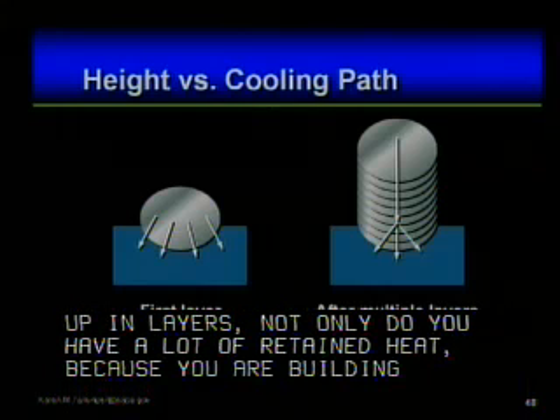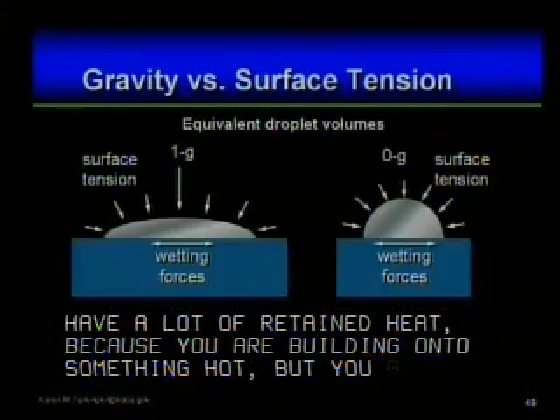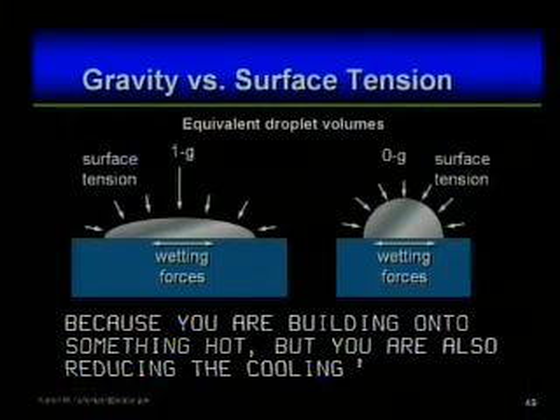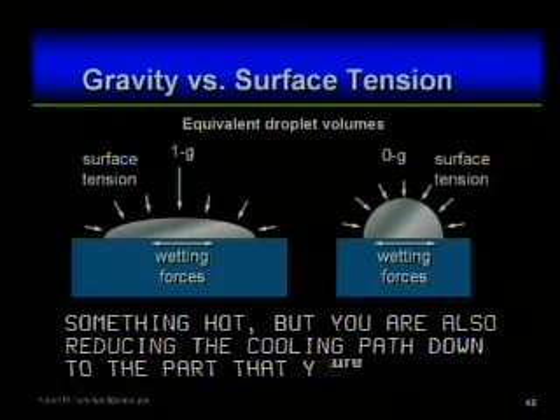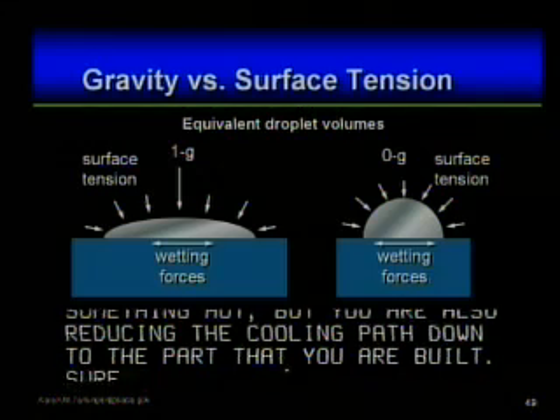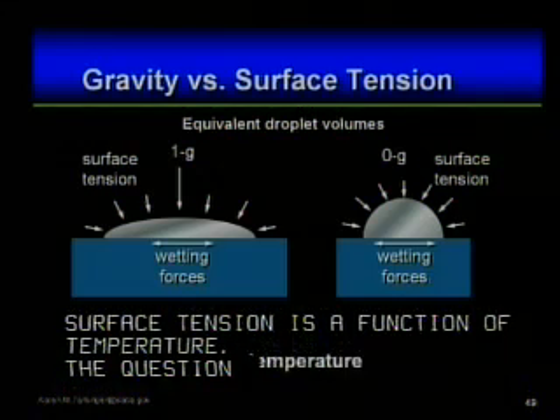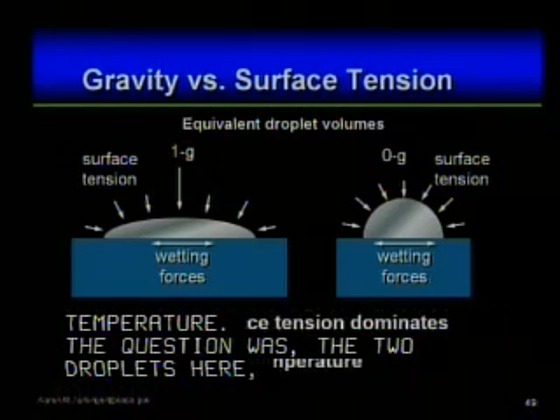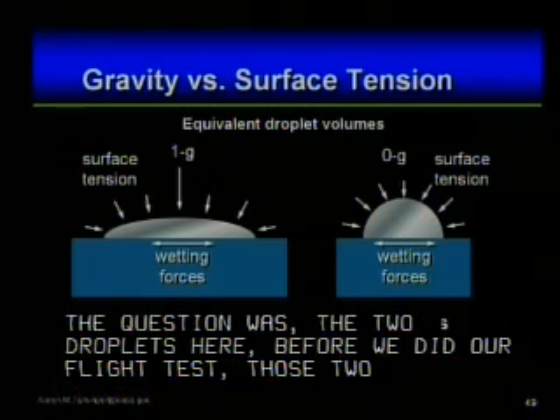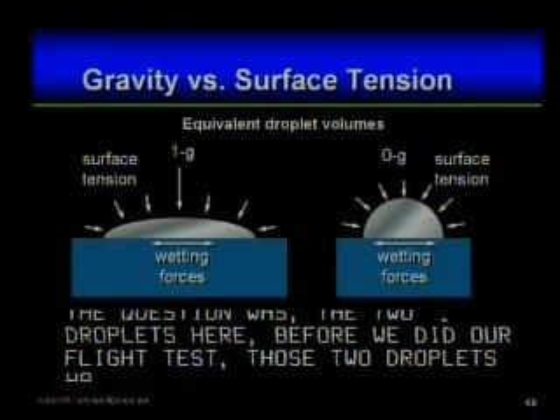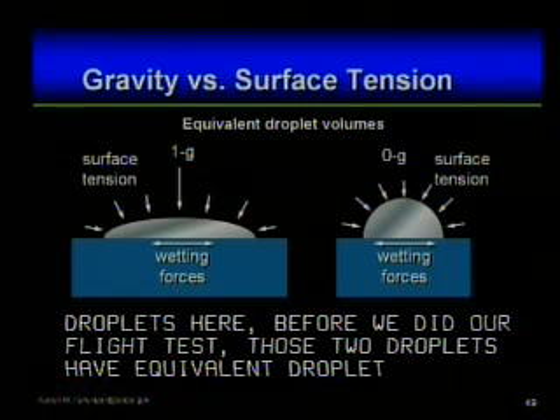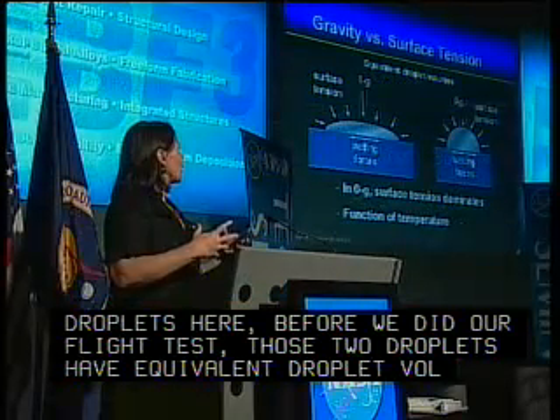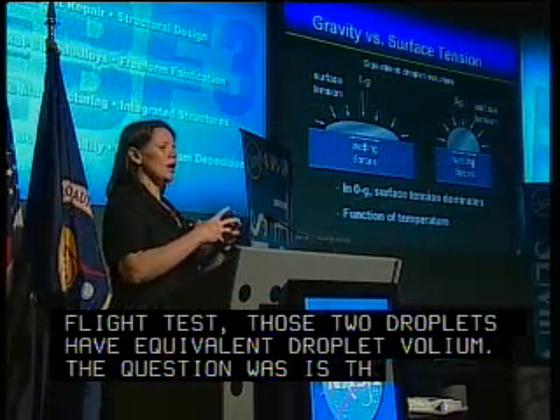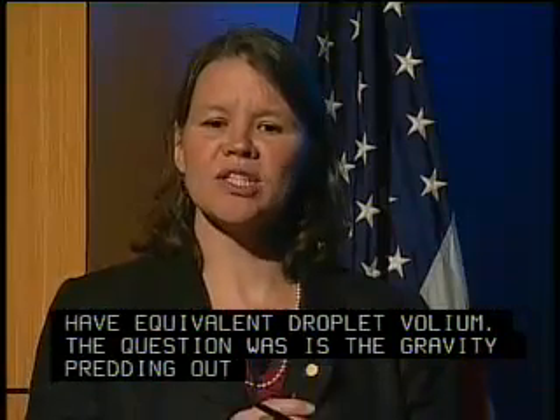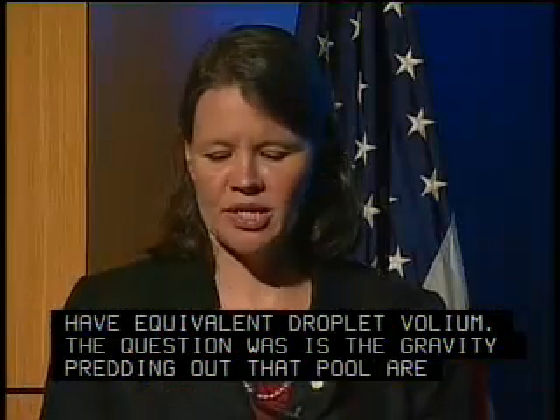And the reason that this is an issue, next slide please, is because surface tension is a function of temperature. And our question was, the two droplets here, before we did our 0G flight test, this is a little bit exaggerated, but those two droplets have equivalent droplet volume. And so the question was, is the gravity working with the wetting forces to spread out that molten pool, or is the surface tension really driving the process, and so that's pulling that bead up into a tight bead?